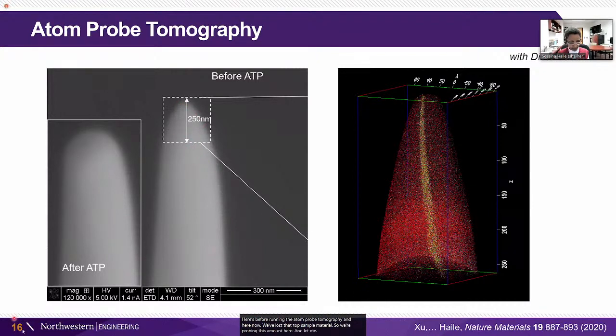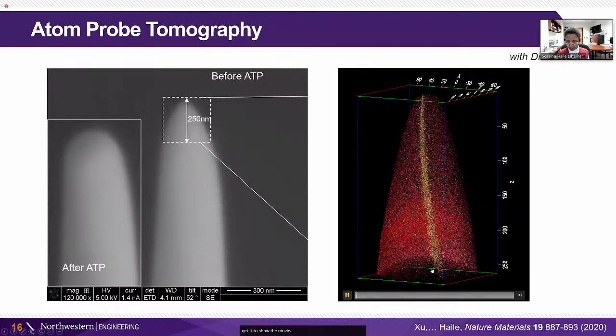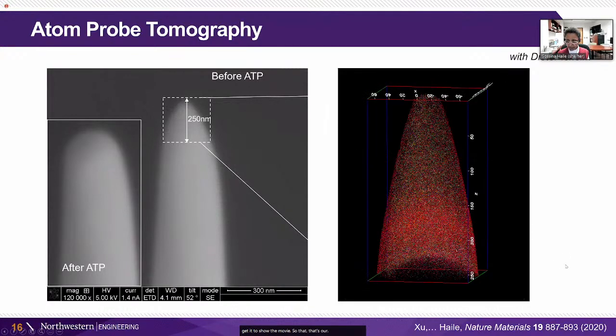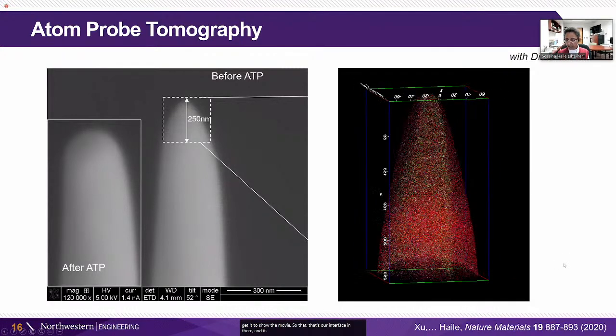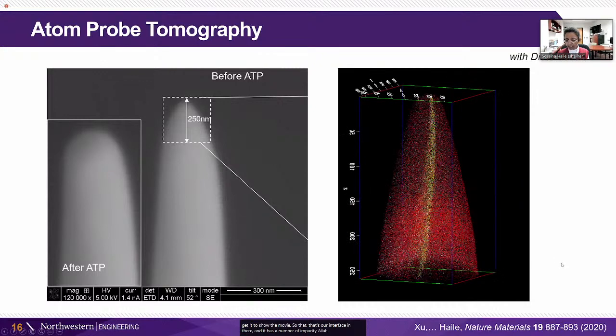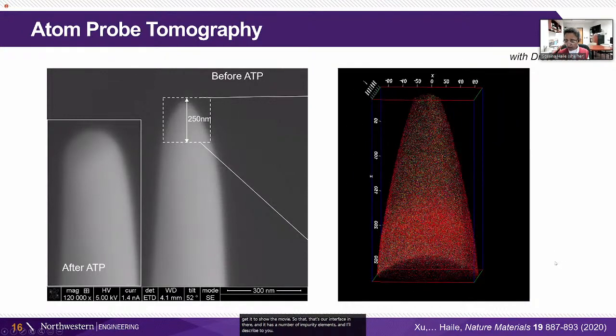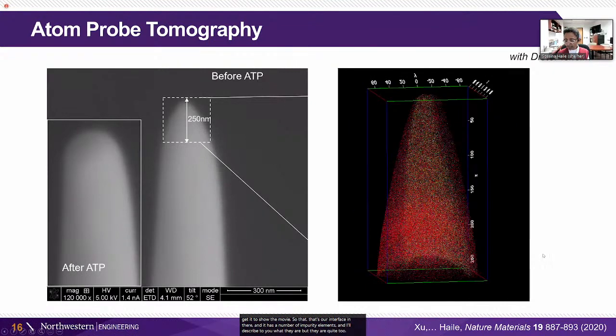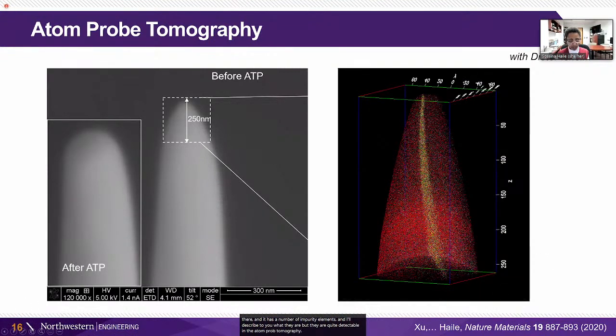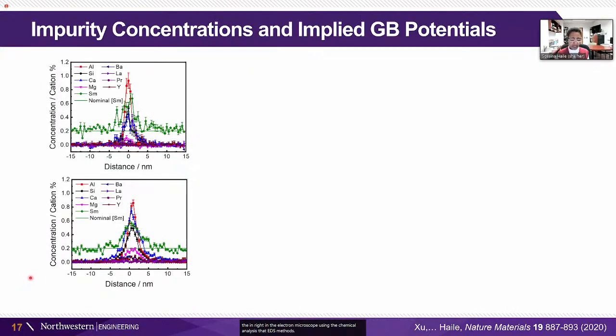And let me see if I can get it to show the movie. So that's our interface in there. And it has a number of impurity elements, and I'll describe to you what they are, but they are quite detectable in the atom probe tomography, whereas we were not able to detect them right in the electron microscope using the chemical analysis, the EDS methods.